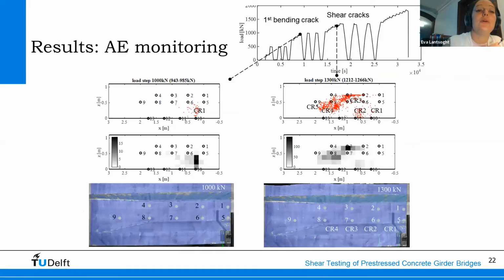When it comes to acoustic emission monitoring, some things that you can see here, based on the analysis of the results, is when we have our first bending crack, we really see hits in the part that indicate that flexure crack, and you see that here based on the post-processing as well. Whereas in this part, we really see the hits in the web, indicating the shear crack, and this relates as well to the load at which we started to see shear cracking.